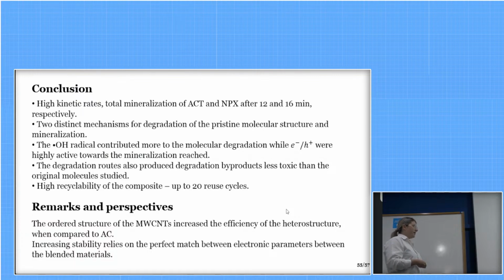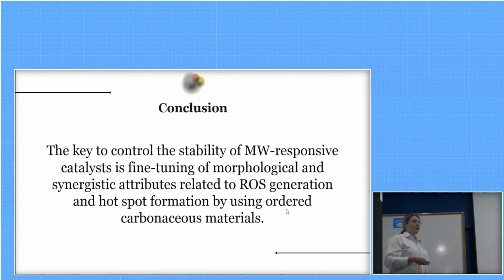Our remarks and perspectives are that the ordered structure of the multi-walled carbon nanotubes increased the efficiency of the heterostructure when compared to AC, and that increasing stability relies on the perfect match between the electronic parameters of the blended materials. So, our conclusion from this thesis is that the key to control the stability for microwave responsive catalysts is the fine-tuning of morphological and synergistic attributes related to reactive oxygen species generation and hotspot formation by using ordered carbonaceous materials.